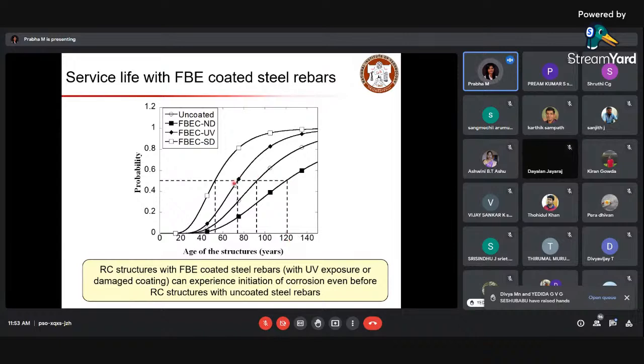Whereas if you look at the UV or surface damage case, the probability of failure is very high compared to conventional concrete systems. So if you take good care of the coating, this technology will help enhance the service life. If not, it will worsen the performance of your structure by increasing the probability of failure and thus reducing the serviceability of your structure.